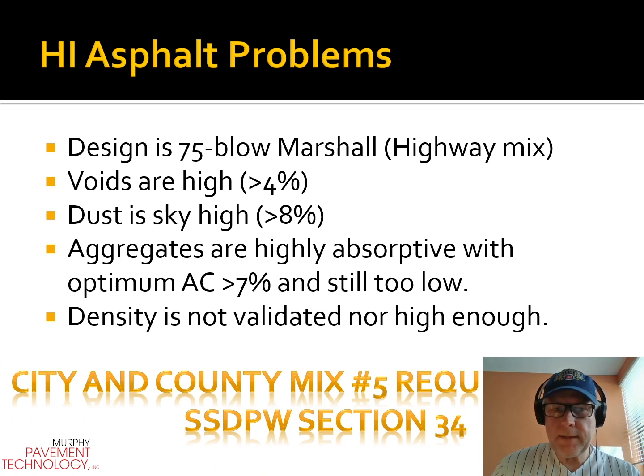A lot of it in different states. This one is Hawaii. They use a highway mix instead of a low volume mix. They have very high air voids. When I told you less than 3 is appropriate, they had the tiny product known as dust or minus 200, which is really high, and very highly absorptive aggregates. Ended up with an optimum asphalt over 7.5%, but it actually required more because of how absorptive the products are.